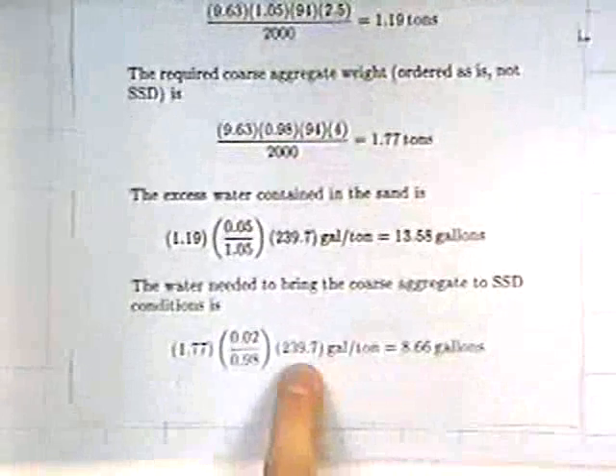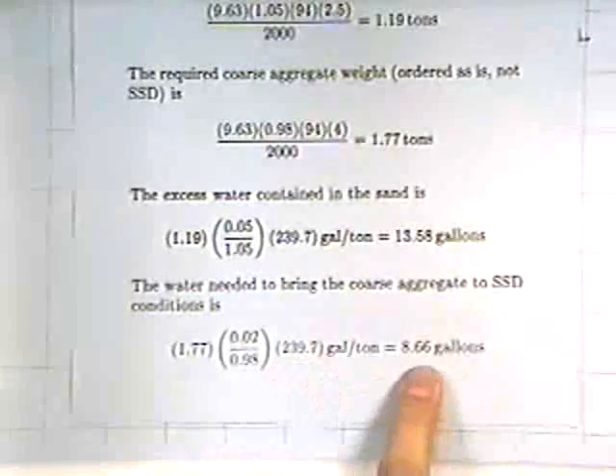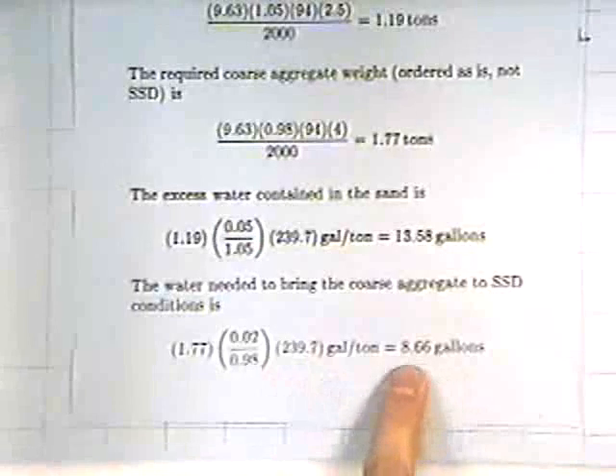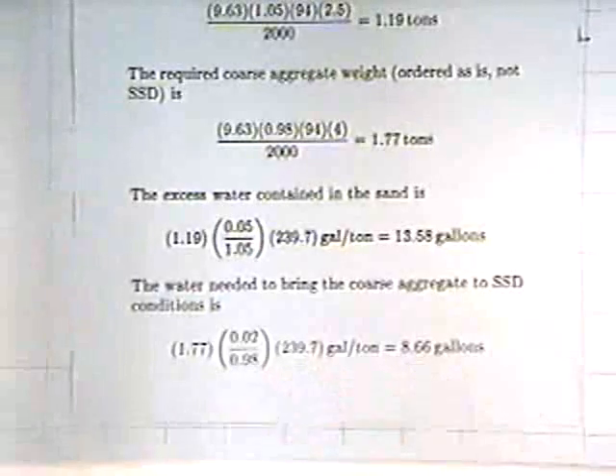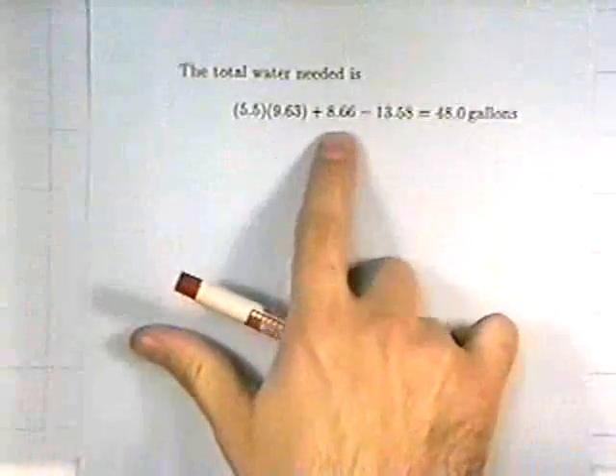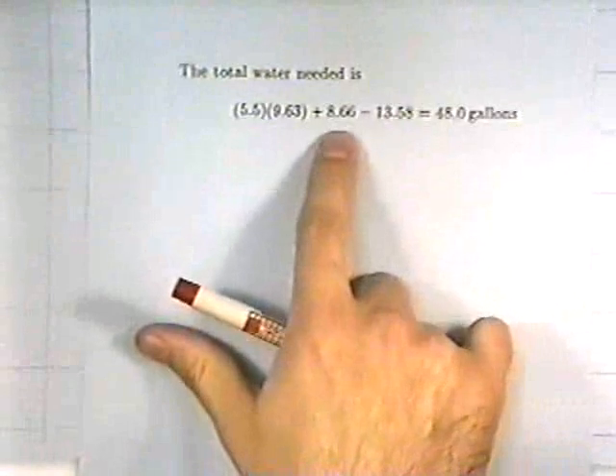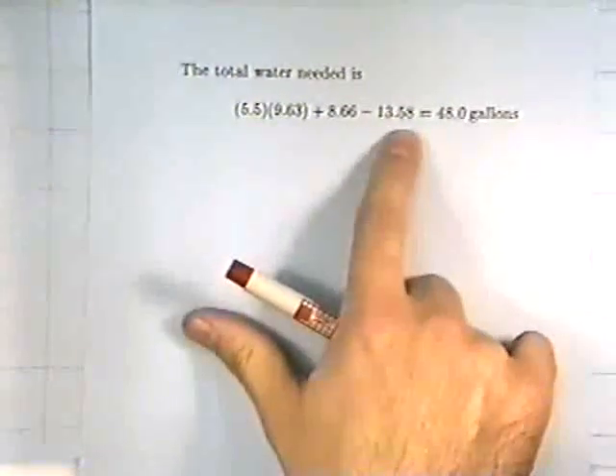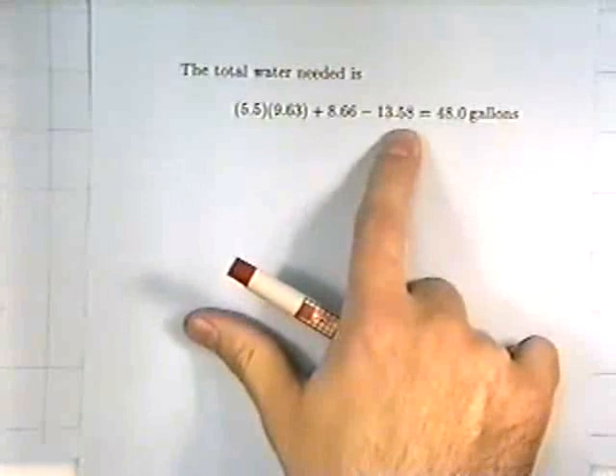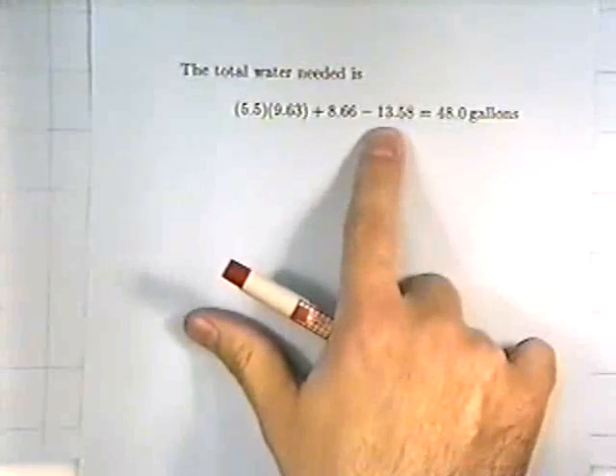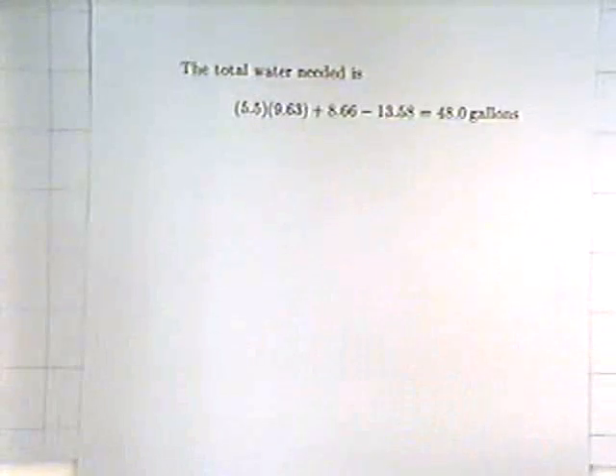Okay, and the same thing goes for the aggregate. You can figure that out. It's basically the same formula with the same constant. This turns out to be a deficit of 8.66 gallons. So your total water requirements are the parts required for the mix, plus the additional part from the sand, which was the 8.66. And we know that the stone had an insufficient amount, and we needed to add on an additional 13.58. This gives us a total volume of water of 48 gallons.